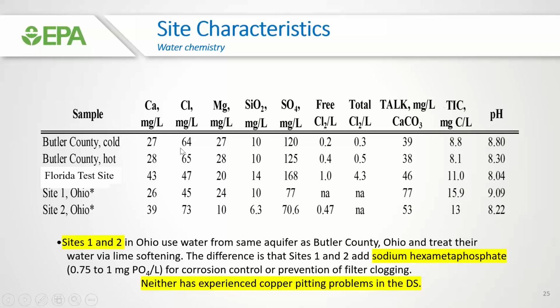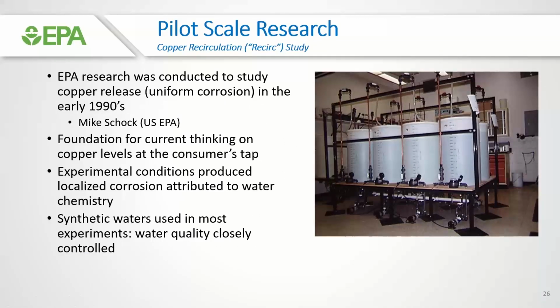Chloride concentrations are significant. But interestingly enough, Site 1 and Site 2 were also communities near the Butler County site, receiving water from the same aquifer, treating it in the same way. Very similar pH, inorganic carbon concentrations are very similar, chloride concentrations are similar, but they had no history at all of pinhole leak problems. Why? Well, as it turns out, Sites 1 and 2 actually use sodium hexametaphosphate in their distribution system. That's important information to latch onto, because that suggests there's something going on, perhaps with the polyphosphate. So it's important, as you think about doing an investigation, to consider what's happening nearby.